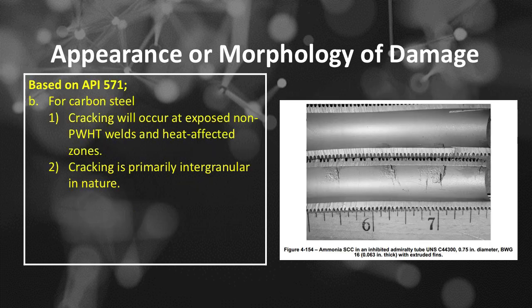Ammonia stress corrosion cracking critical factors based on API 571, number B, for carbon steel, include: number 1, cracking will occur at exposed non-PWHT welds and heat-affected zones; number 2, cracking is primarily intergranular in nature.